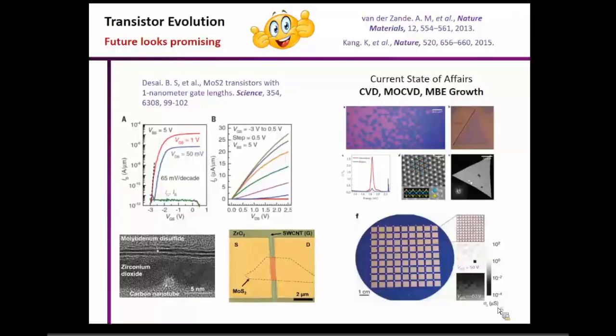And because of the fringing field, you will probably have a little bit larger gating area. But this is a very interesting result where they kind of show pretty much not a lot of short channel effects, and they get very decent performance from these devices. So you can scale these devices down to 1 nanometer length, which has already been demonstrated. But then this is only one piece of device and actually being made on an exfoliated flake.